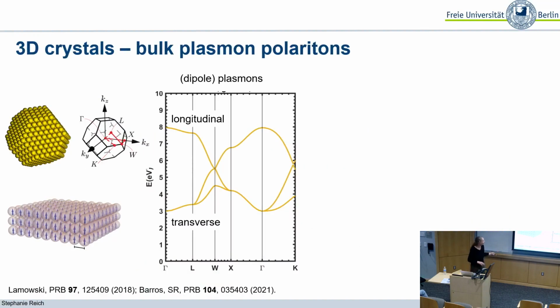Let's take such a crystal of gold nanoparticles and describe it theoretically by putting a dipole into each of these nanoparticles and then letting all of these dipoles interact. So we're deviating from what I showed you for the cavities, where people don't care about the interaction between the dipoles. We now deliberately look at the dipole-dipole coupling. If you do that, you can write down a Hamiltonian for the plasmons, and you will get a dispersion for the plasmons inside this supercrystal, a crystal made out of these nanoparticles. I want you to focus on the gamma-L direction here, because that is the one that we are later going to use in the experiment.